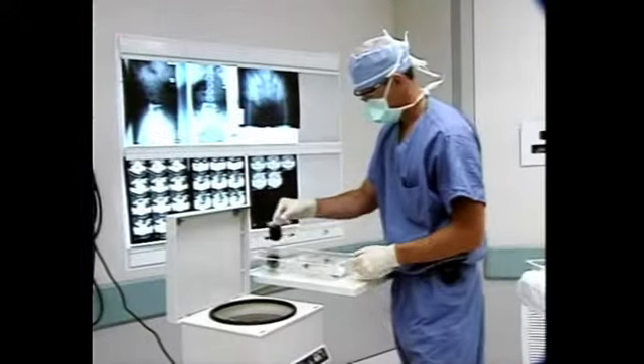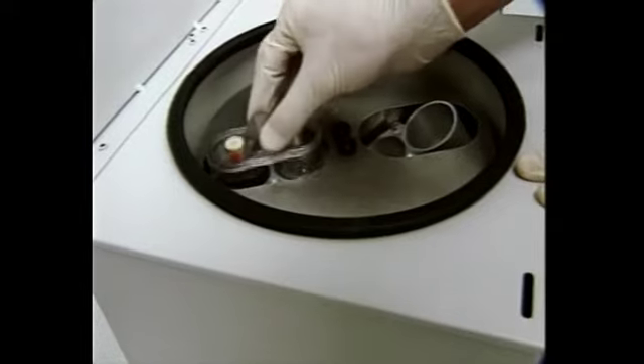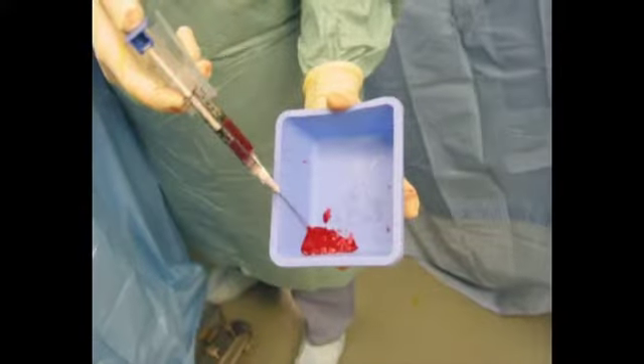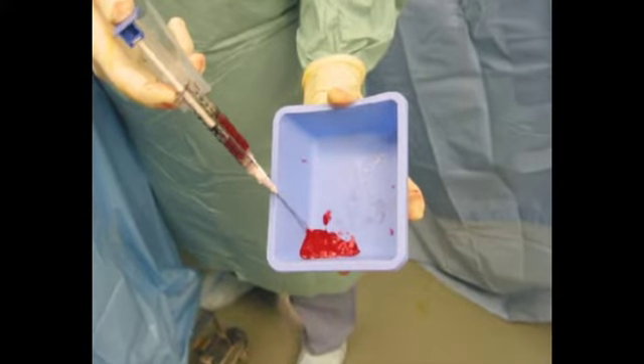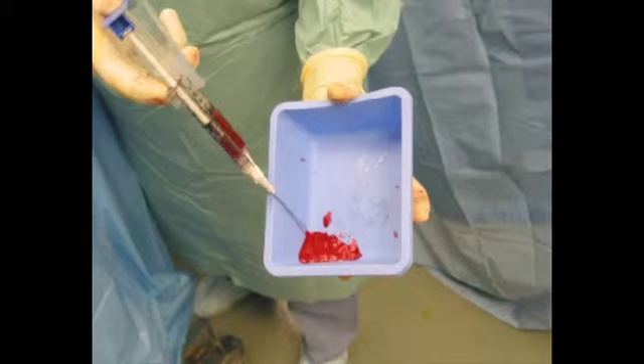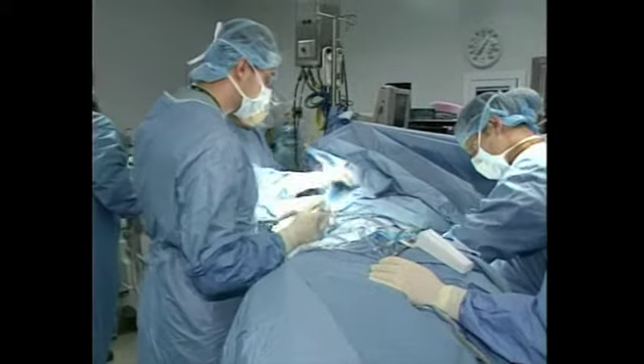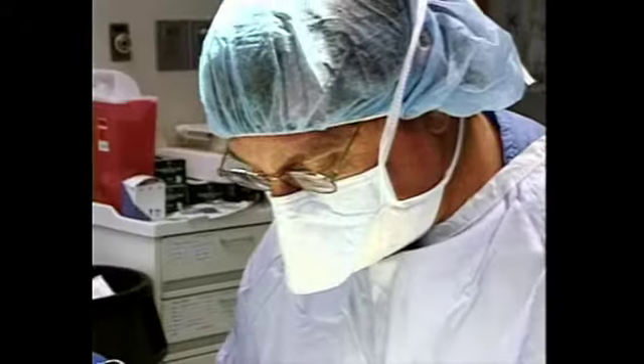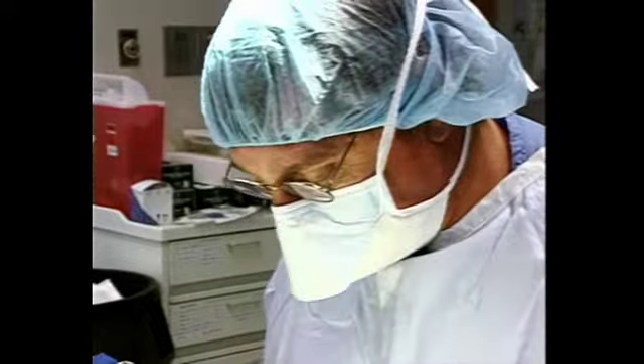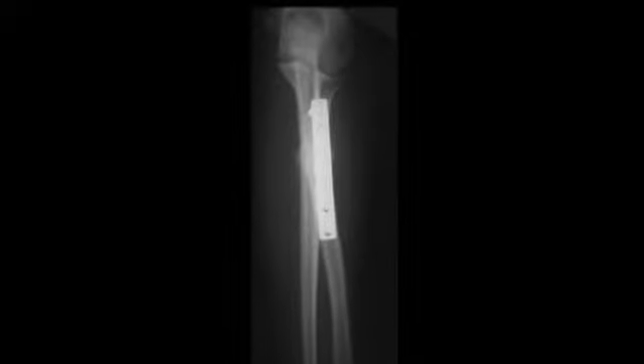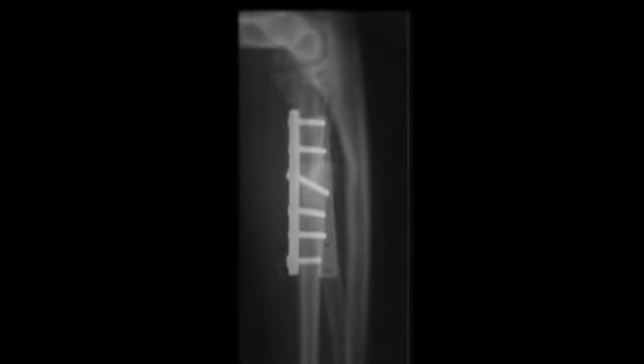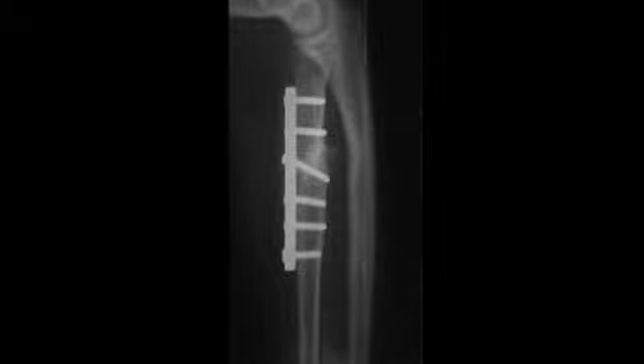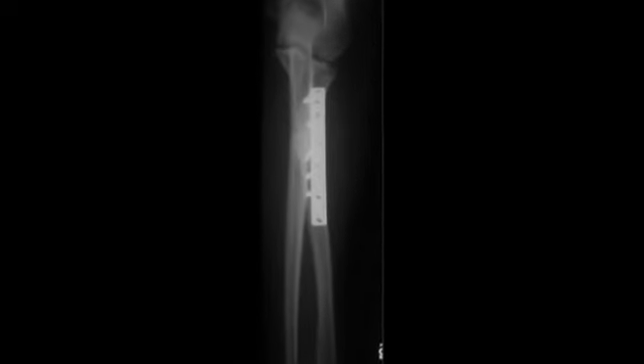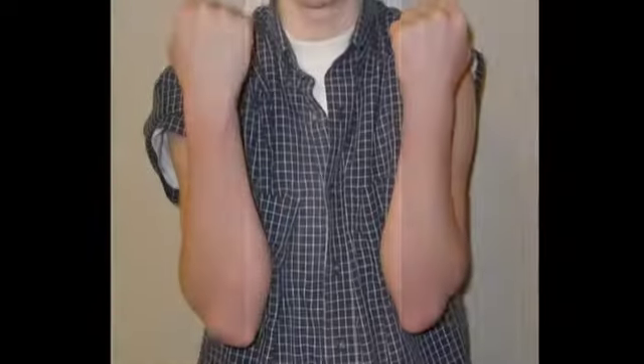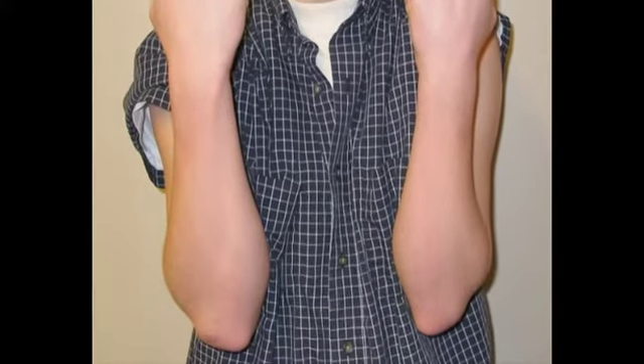A combination of 1 cc of harvested proximal ulnar bone graft combined with 2 cc's of platelet-rich plasma was used as the bone graft material. The nonunion site was prepared with open exposure, removal of fibrous tissue, and burring the bone ends to puncture bleeding points. Internal fixation with compression plating was performed. Early healing was evident at 6 weeks, and X-rays at 10 weeks post-repair demonstrated further union. Clinical photographs demonstrate restoration of functional range of motion.